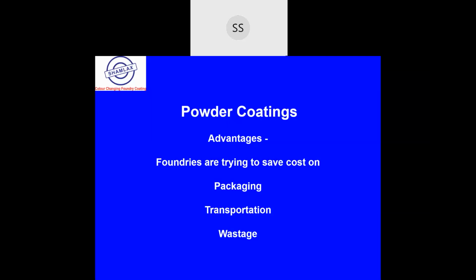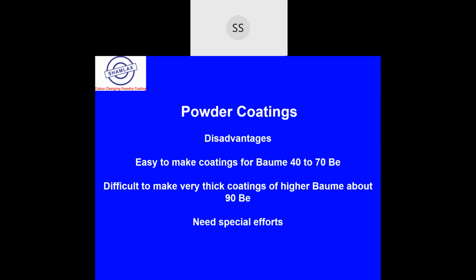The disadvantage is that it is easy to make coatings only for a Baume of 40 to 70 degree Baume, not more than that. At 40 Baume, mostly the automobile castings foundries use aluminosilicate based coatings. They get basically a thick coating and then dilute it to a Baume of around 35 to 40, and then use it for the cores and the molds.